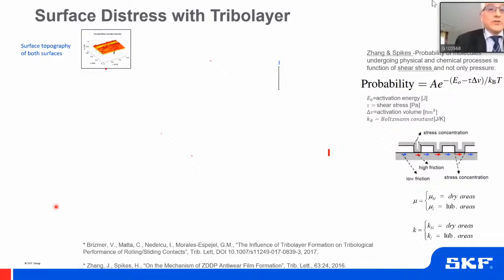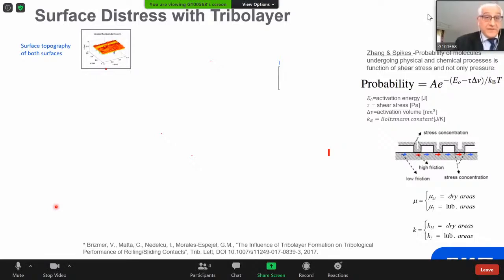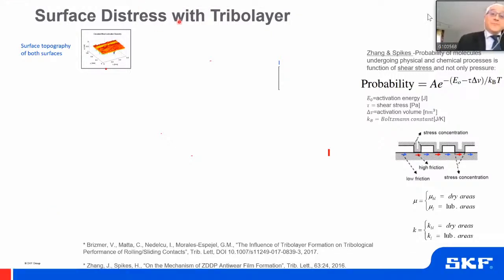But if you really want to model this phenomenon, you need to take into account many, many things. You need to take into account the actual topography that you are testing. You need to take into account also the build-up of tribofilm from the additives. And for that, we use the work of Dr. Zhang and Professor Spikes at Imperial College, who have established that the tribofilm reaction depends on the shear stress and depends on the temperature. It's important to say that because in the past we used to believe that it depended on the pressure, but he has shown that it depends on the shear stress. So we need to be able to calculate locally the shear stress.